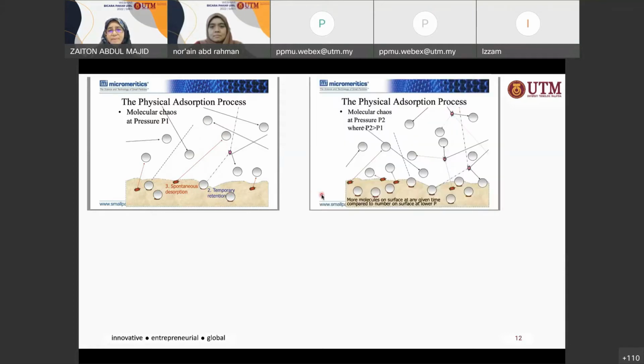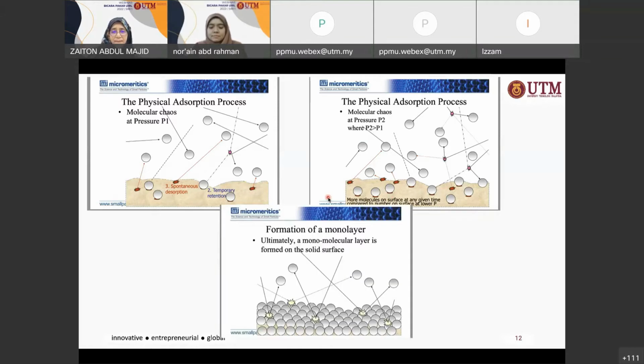And then as the pressure increases, so P2 is greater than P1, you're going to have more molecules on the surface at any given time compared to the number at lower pressure. So the greater the pressure, the more molecules are going to be adsorbed onto the surface of your solid. Finally, you have the formation of the monolayer. So a monolayer in this case, for example, means all adsorption sites are occupied. Based on the Langmuir theory, once it's occupied, you no longer can have any more adsorption. This is based on the Langmuir theory. But then according to the BET theory, you can have multi-layer formation after this.